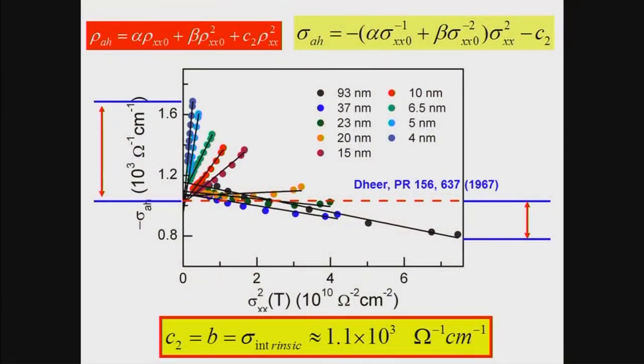So once you have this scaling established, you can convert it to conductivity, and this can be calculated easily. So for all the different film thickness, the low temperature data could be anywhere, it's fan-like, but when the temperature increases to about room temperature, it's merging to a kind of universal point. And this value around 1,000 is this intrinsic contribution.